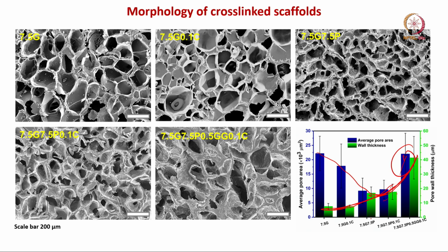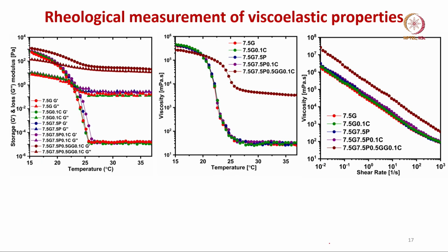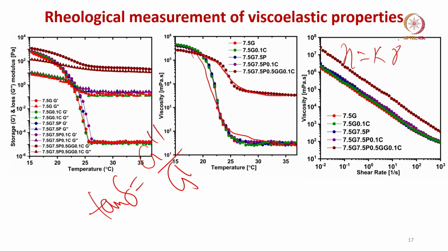This is the scanning electron microscopic image, and this scale bar is essentially 200 micron. Now, rheological analysis of the viscoelastic properties. So, you have the storage modulus. I repeat, your tan delta loss factor is G double prime by G prime, and then what you can see here is that viscosity as a function of temperature also goes through a very rapid decrease. So, eta is equal to k gamma dot to the power n minus 1, and as I told you, the slope is essentially n minus 1 because it is plotted in the log scale, right.